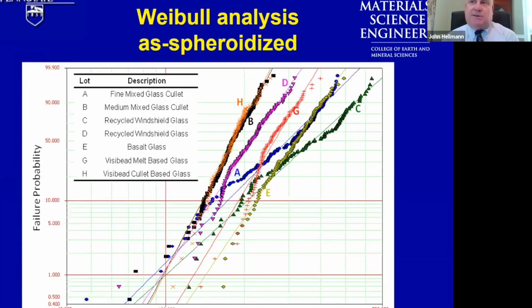We used Weibull analysis to characterize the strength distributions. These are Weibull distributions based on hundreds of individual fractures in diametral compression of a variety of different glass bead materials. We use this methodology throughout because it enabled us, number one, to understand the characteristic strength, number two, understand strength uniformity, and number three, we could then use that data to calculate the onset of failure and strength of any bead of comparable composition and treatment, but of a different size or under a different loading characteristic.